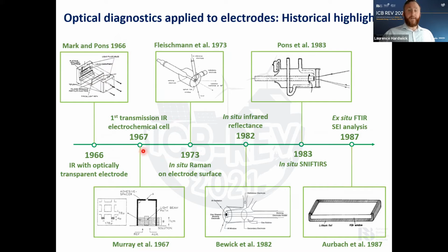And this is then the first transmission infrared cell. You have a gold mini grid, and they were looking at the redox chemistry of certain organic materials in this transmission cell. Then in 1973, this is where in situ Raman was first reported, and this was by Fleischmann, and he was looking at the surface of mercury electrodes under potential control. And so this is the birth of in situ Raman, and the very next year, his next paper, where he was looking at a roughened silver electrode, was the first reported observation of the surface enhanced Raman effect.